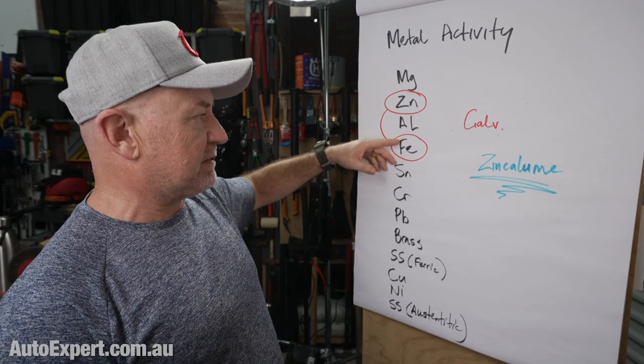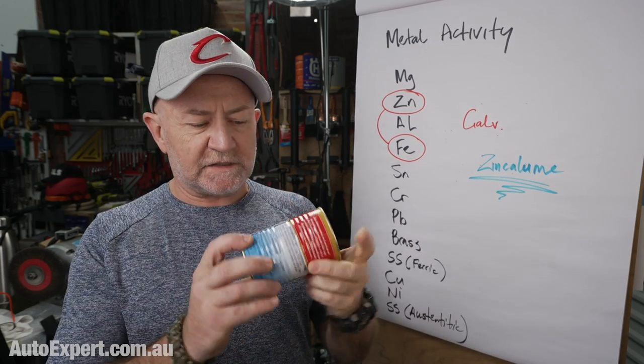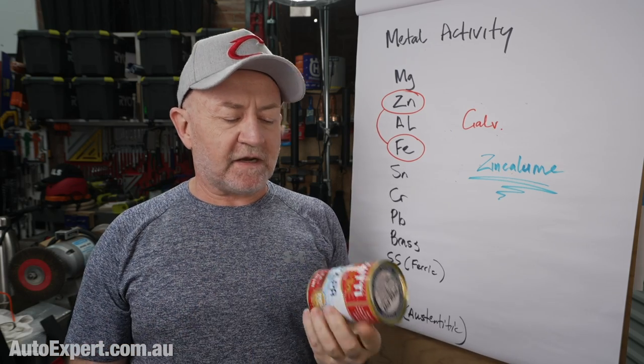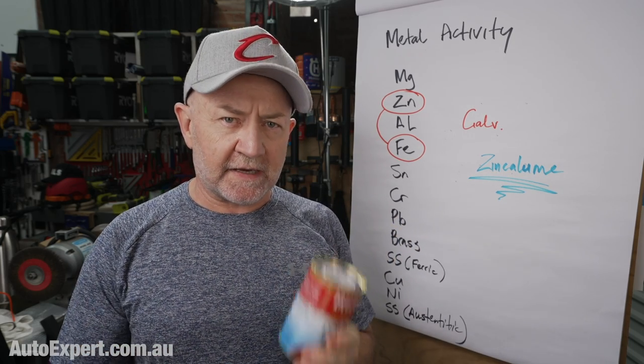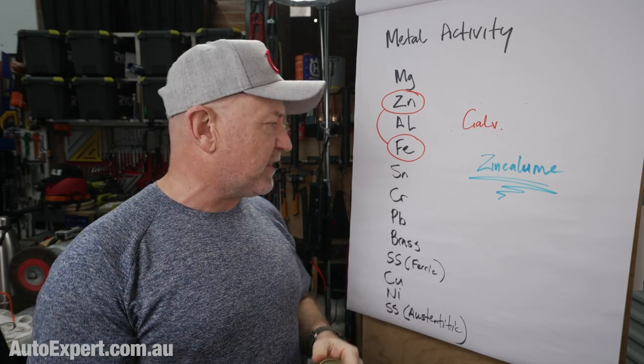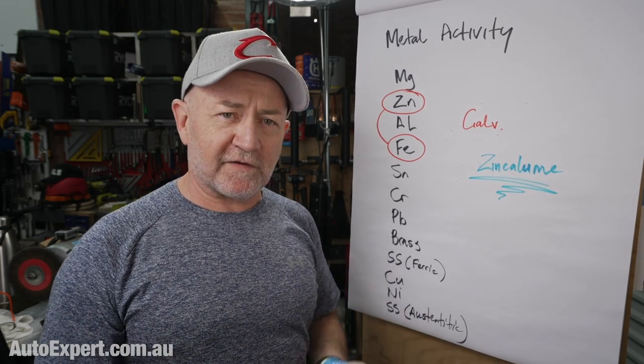When you look at the activity series — magnesium, zinc, aluminium, and iron — tin is quite interesting. Tin provides a completely different kind of protection that relies on complete integrity of the tin as an envelope around the underlying steel. But if you cut out a bit of a tin can's sidewall, nail it on a fence, and leave it for a fortnight, you'll see the difference from galvanised steel: steel is the more active metal and tin is the less active metal, so the steel will actually sacrifice itself to protect the tin, accelerating its own destruction. So it's important to get the metals right. Something like chromium — way down in activity — is why rust forms on chromed spanners: it's durable, but a defect causes rust to burrow under just like paint.